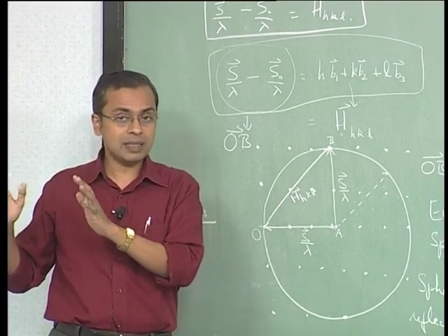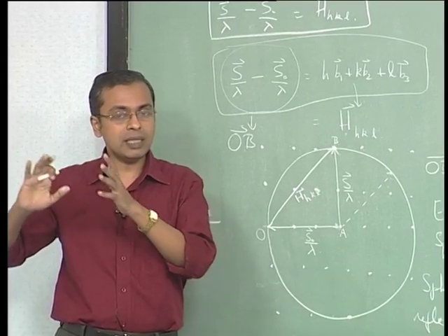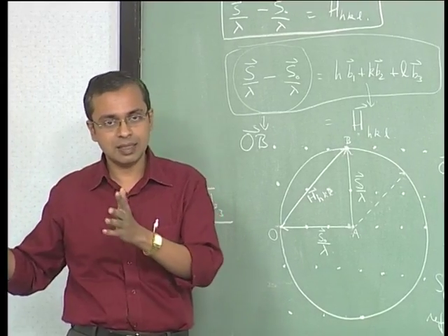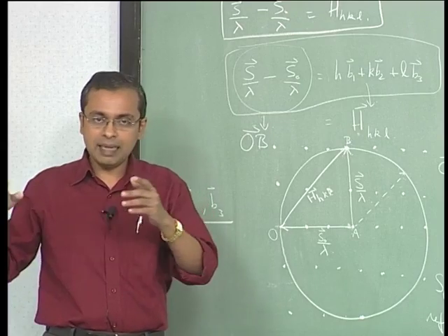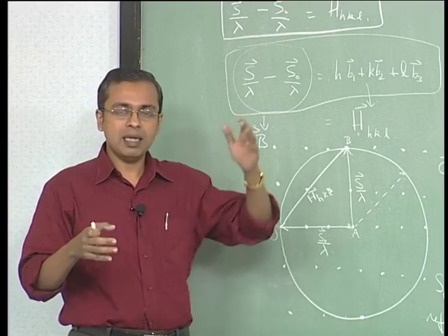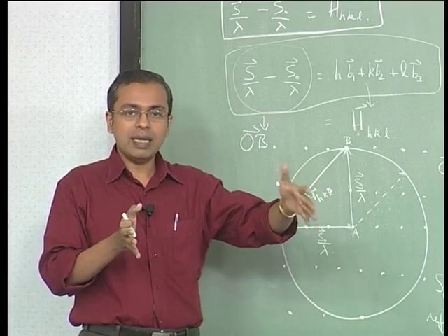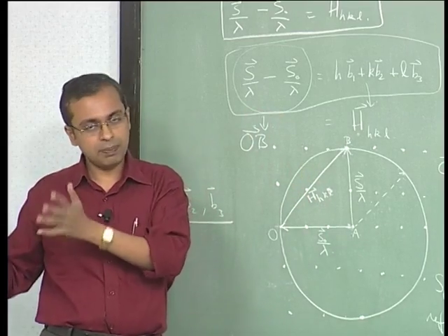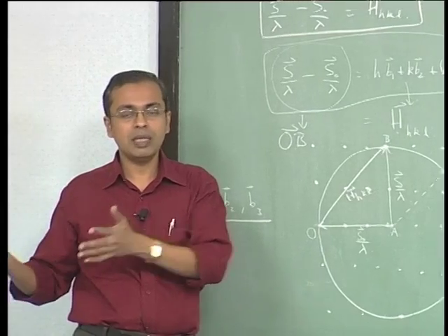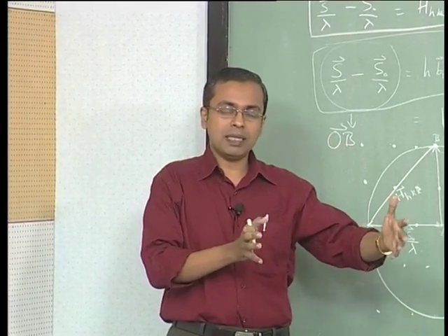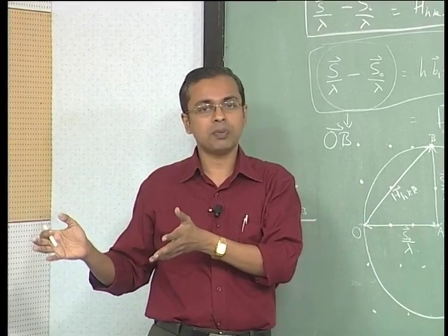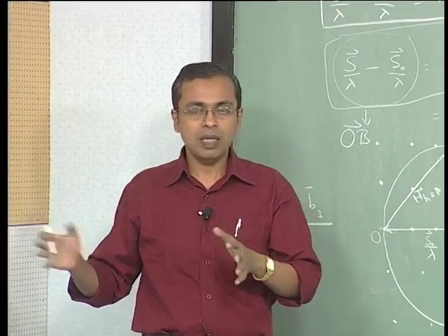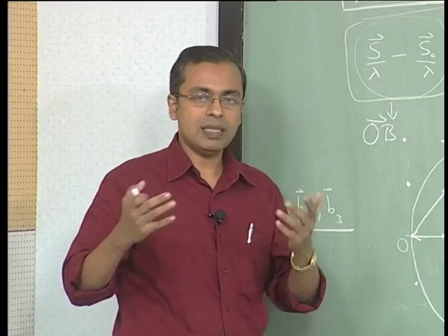The information is still the original material's information; it is only the representation in reciprocal space that has a certain layout. It so happens that when you take a face centered cubic material, its representation in reciprocal space is that of a body centered cube, and if you take a body centered cubic material, its representation in reciprocal space is a face centered cube. So these are all independent pieces of information that we will keep in mind.